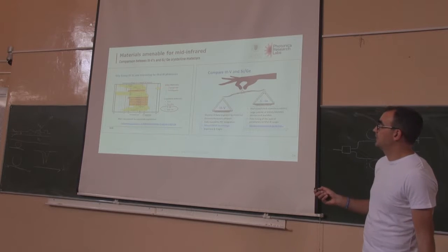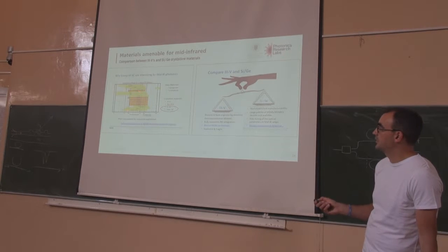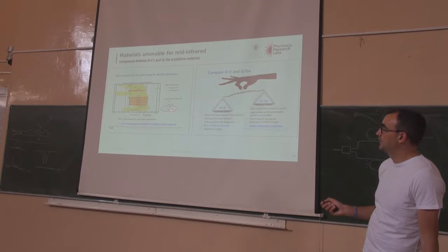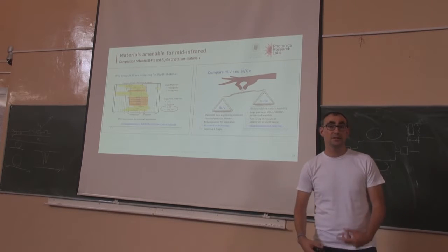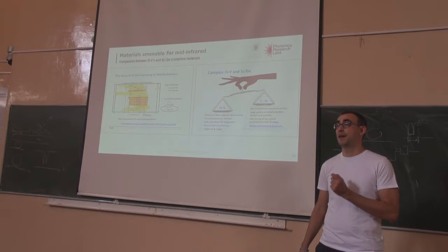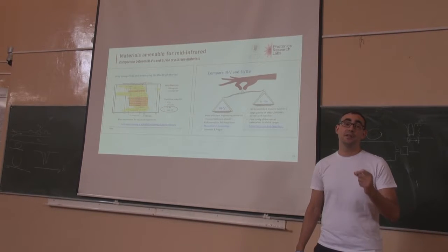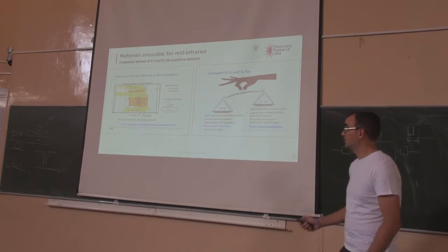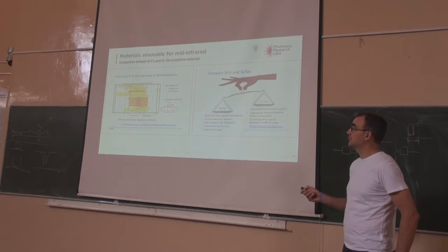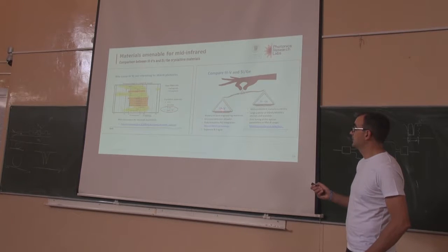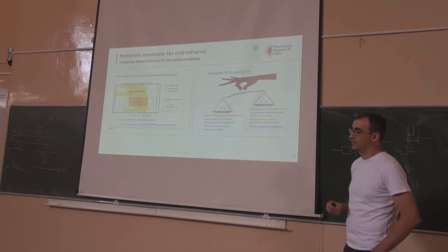Well, there are many types of material, glass and crystalline materials, and you can see the transparency ranges and the wavelength here. But there are a few, like silicon, germanium, gallium arsenide, indium phosphide, which can be used in those wavelength ranges, but that are also amenable to manufacturing using photolithography steps. So once again, one key determining factor for deciding on a material system is whether it can be produced in mass volumes. Both silicon and germanium, gallium arsenide and indium phosphide can. Now if you compare the 3-5s and the group four elements, silicon and germanium, there are a little bit more drawbacks for the 3-5s.